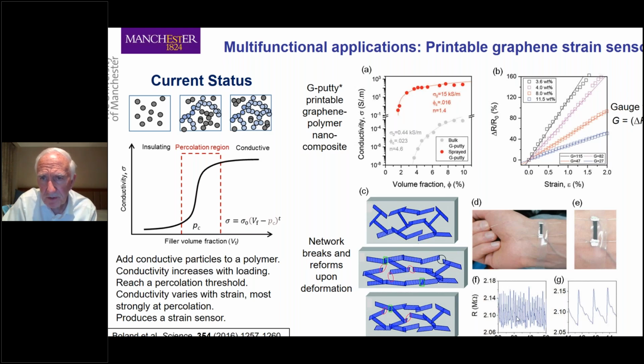And if you measure the resistance as a function of time, you can see that it goes up and down. And if you look at it in more detail at the 1 second scale, you can see that you're getting pulses about every second. And that allows you to measure both the pulse, and also from the shape of this curve here, you can actually also measure the blood pressure. And that's a very simple example of how you can use these printable graphene sensors for strain monitoring. Now, that's the current status, and I want to talk about perhaps new developments.